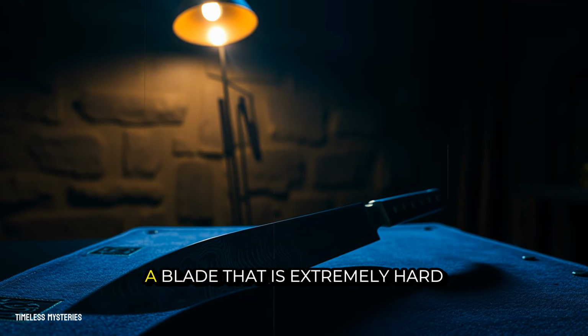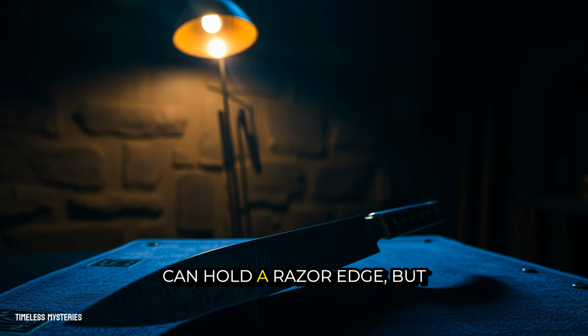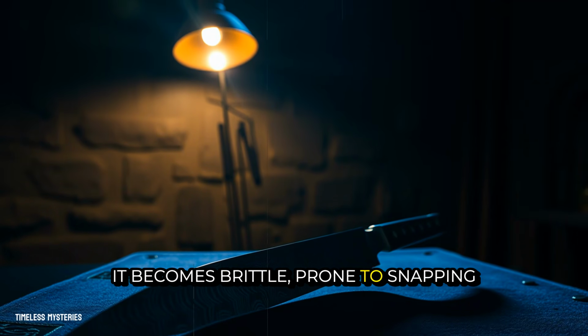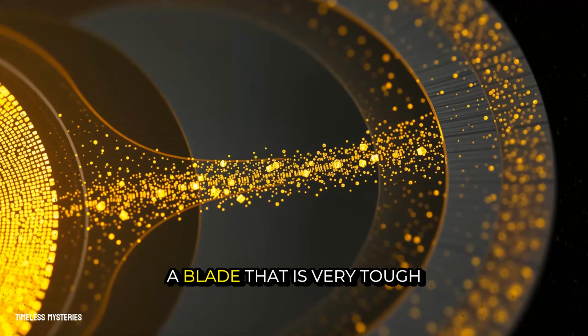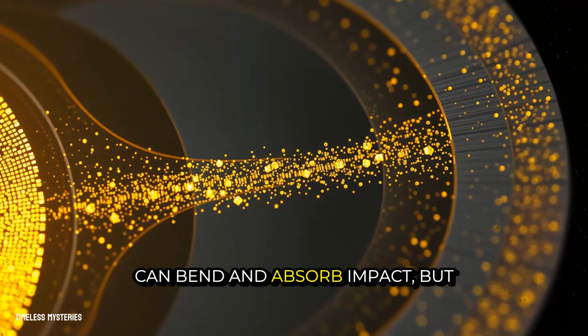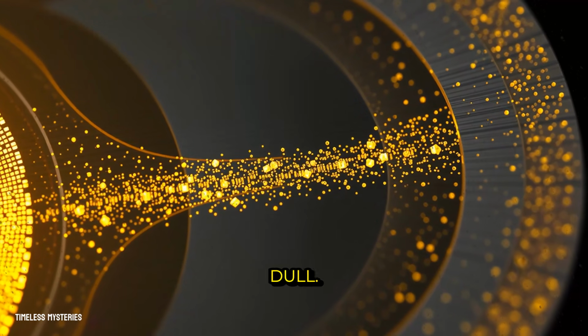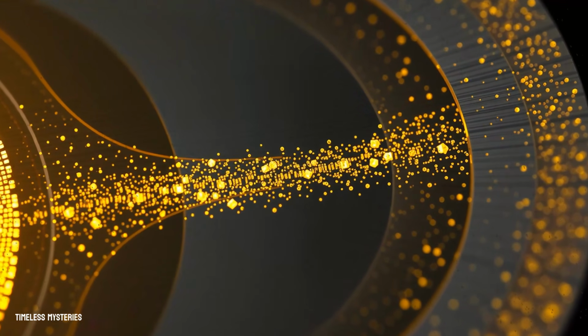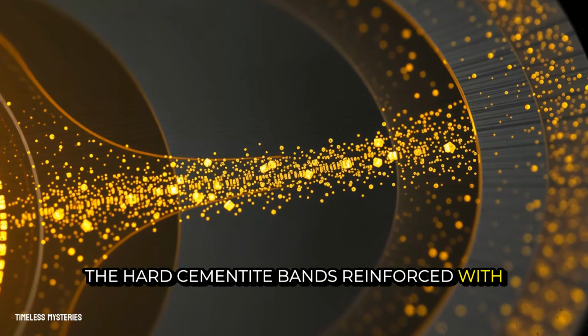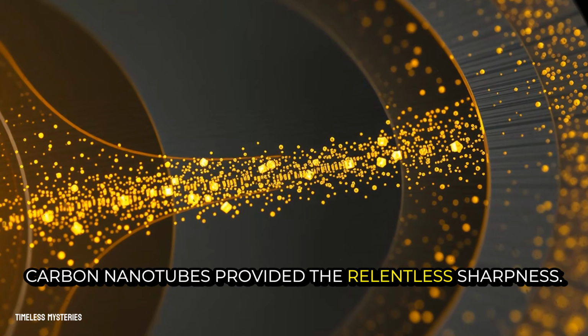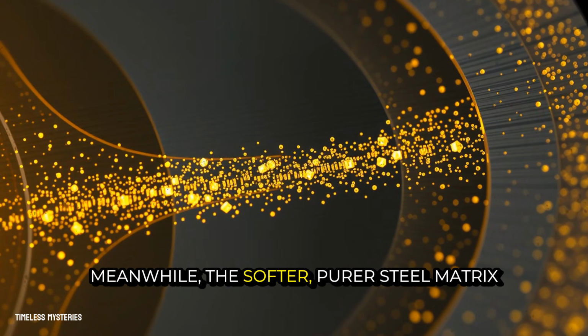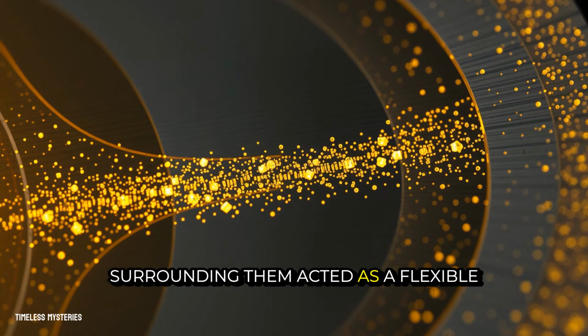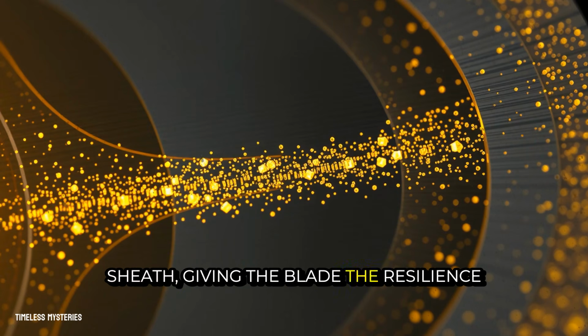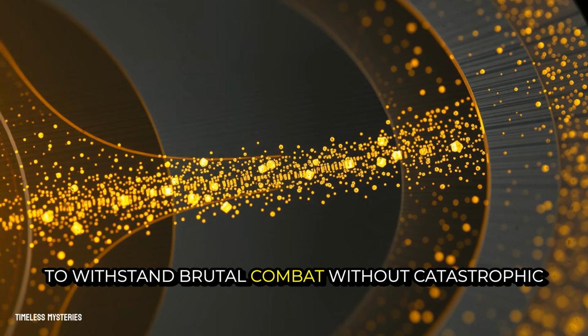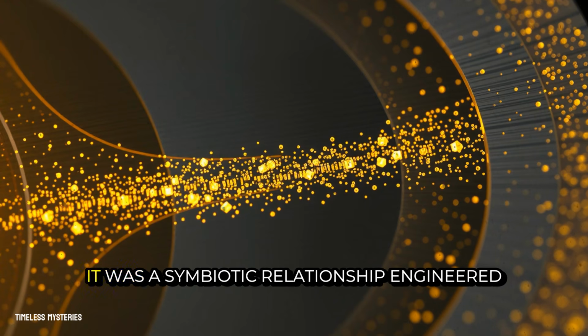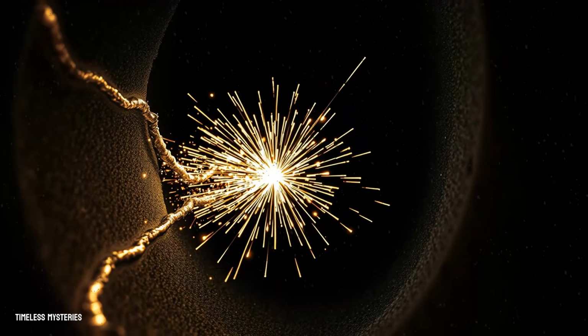in metallurgy. A blade that is extremely hard can hold a razor edge, but it becomes brittle, prone to snapping under a heavy blow. A blade that is very tough can bend and absorb impact, but its edge will quickly roll and dull. Damascus steel achieved both. The hard cementite bands, reinforced with carbon nanotubes, provided the relentless sharpness. Meanwhile, the softer, purer steel matrix surrounding them acted as a flexible sheath, giving the blade the resilience to withstand brutal combat without catastrophic failure. It was a symbiotic relationship engineered at the atomic level.